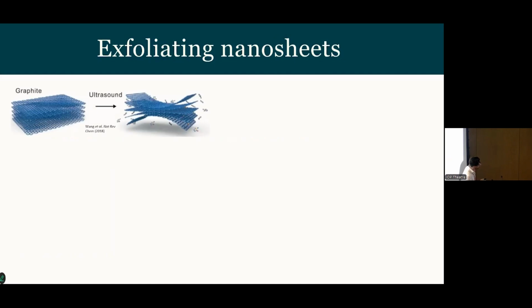Okay, so the materials I'm going to talk about today are nanosheets, 2D materials, graphene and molybdenum disulfide specifically. We prepare these by exfoliating from bulk crystals such as graphite, using ultrasound and a carefully selected combination of solvents, surfactants based on surface tension matching and Hansen solubility parameter. I will add, I'm a physicist. I've done materials work for a while now. Most physicists think we're chemists, so I won't be offended if it feels the same.